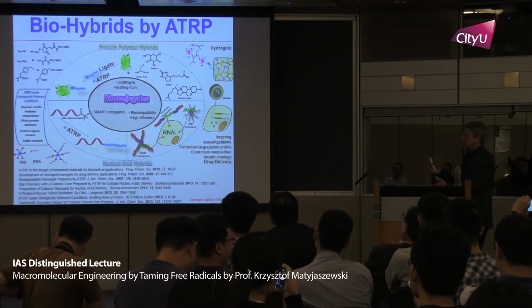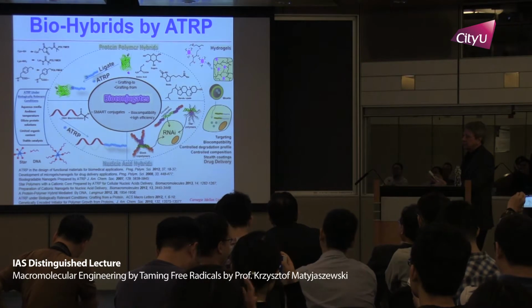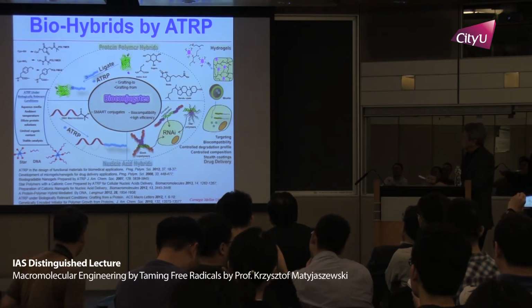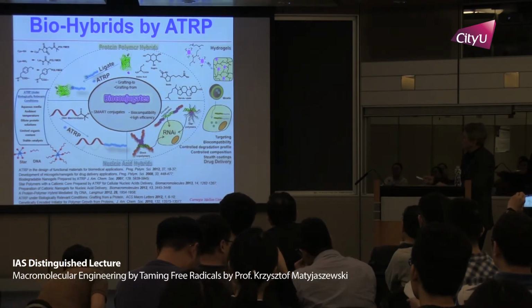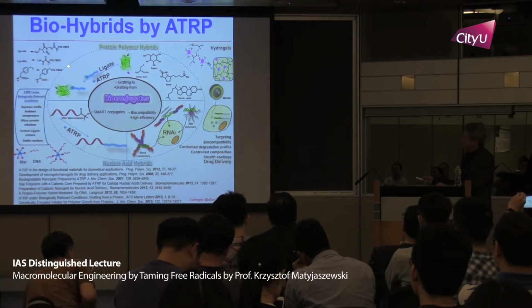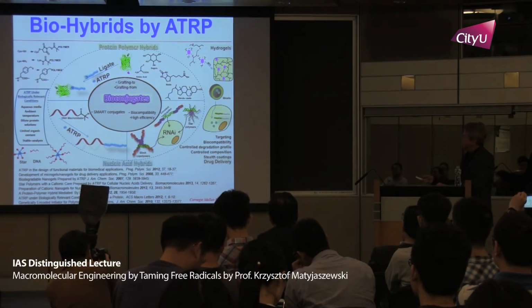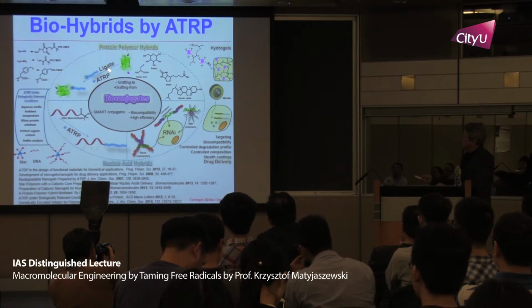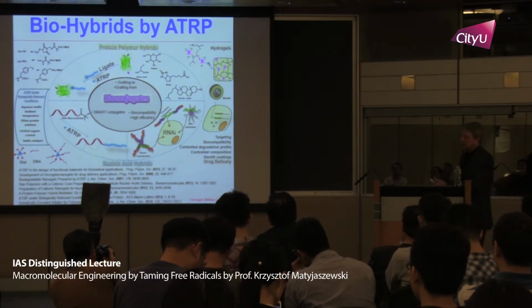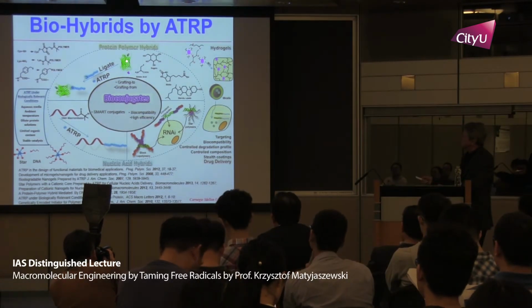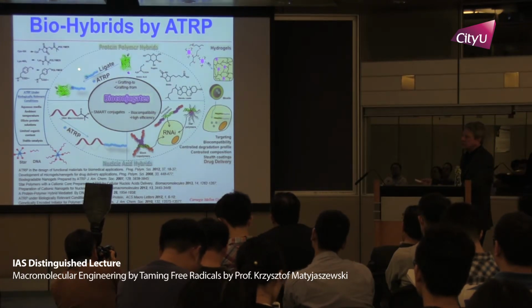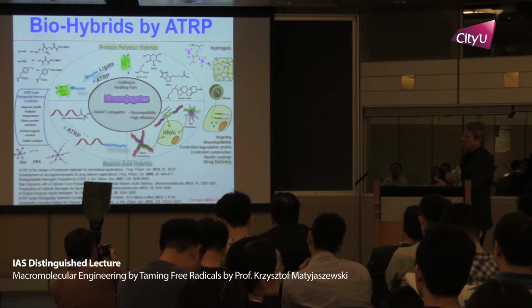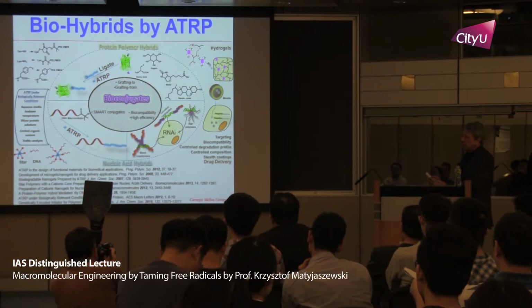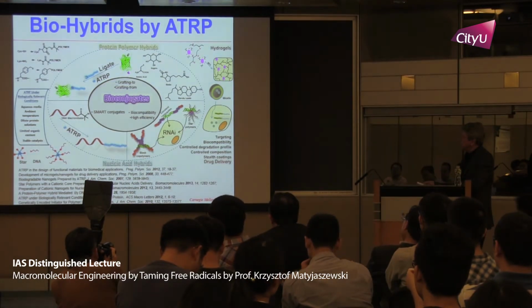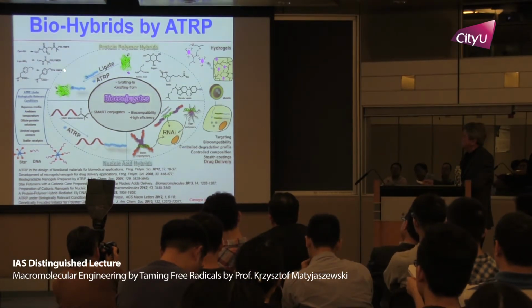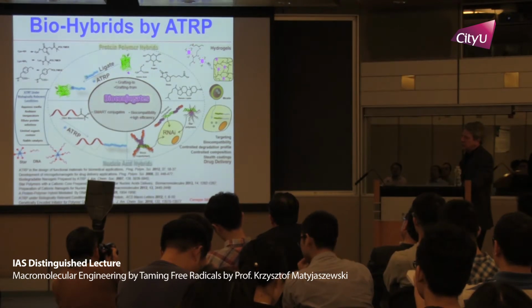And this is an area which really did not exist 10 years ago, because previously most people were conjugating polymers, like pegylated structures, onto proteins using a very large excess of the corresponding polymer structures. So if this is, let's say, 50,000, you need to use maybe a 50-fold excess of the polymer, run under very dilute conditions. Very difficult to separate unreacted pegylated structure.